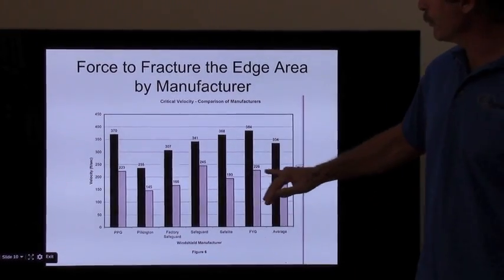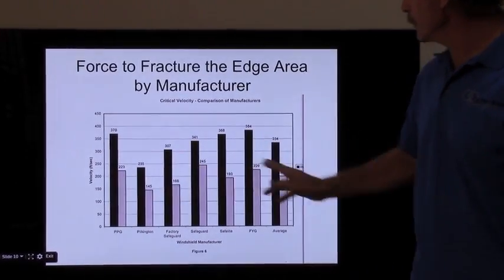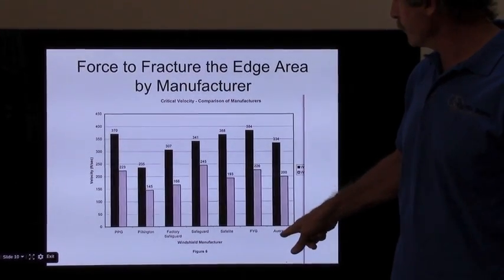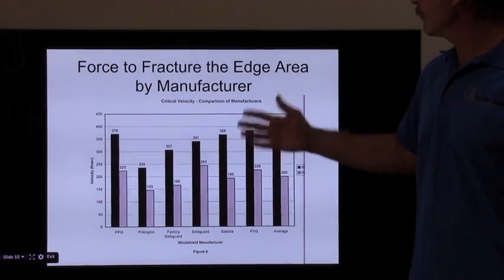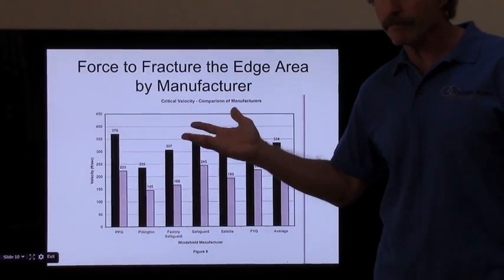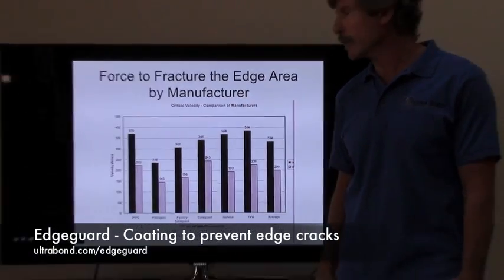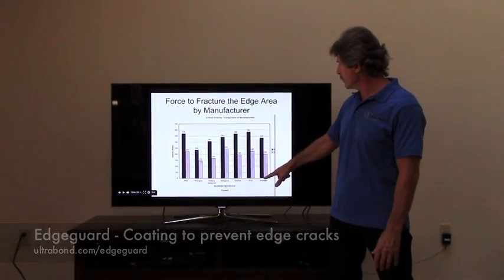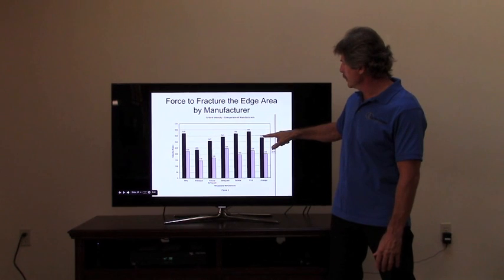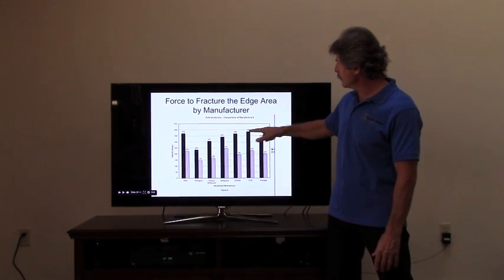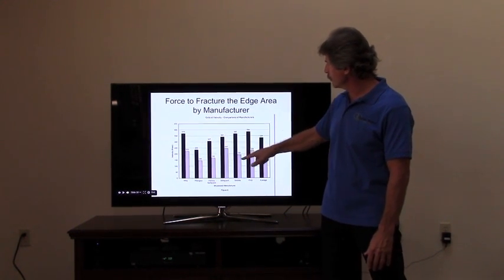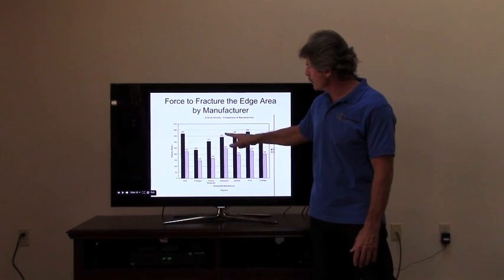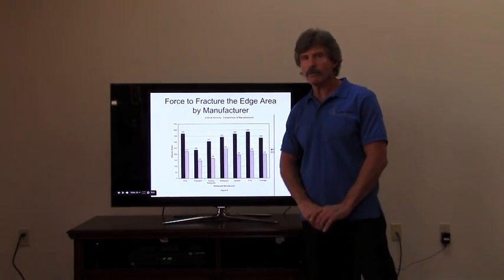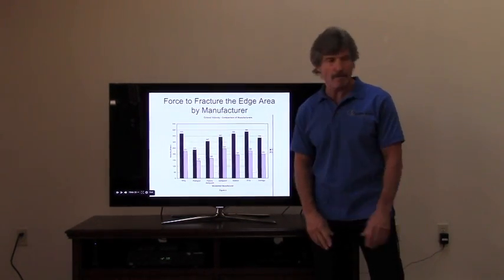But the point that we were trying to prove is that overall, all these windshields fracture easier on the edge. We also have a product called Edge Guard. Edge Guard is a coating that goes over that weak spot to prevent edge cracks. And this shows you what the Edge Guard improved that weak spot to. This is how much harder it was to fracture in the edge area weak spot when we coated it with one of our many Edge Guard coatings.